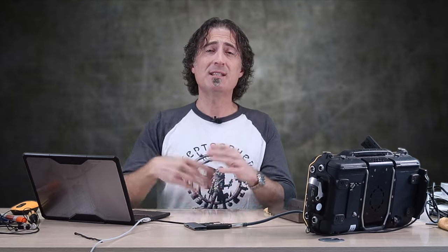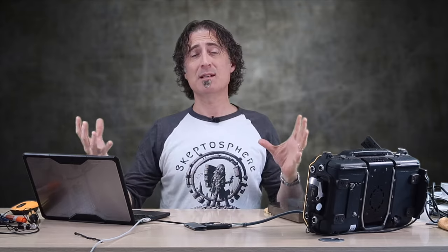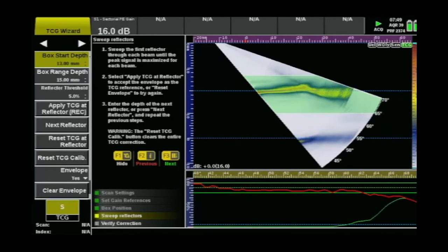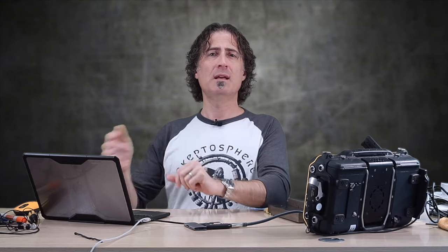But by the nature of a TCG calibration, it's going to pull those low amplitude signals right back up to 80%, so everything looks the same. So if I verify the TCG, here's what you see. Number one is just that sensitivity drop due to the fact that it mode converted, so we get a huge boost in the TCG at around 60 degrees.